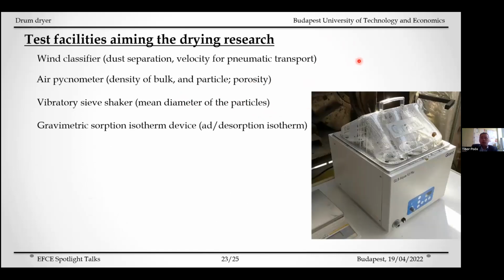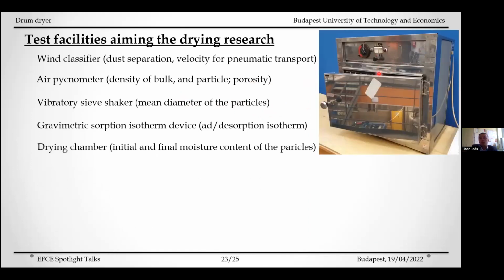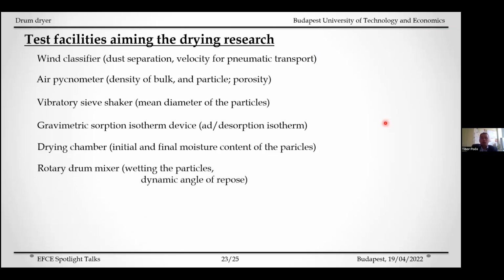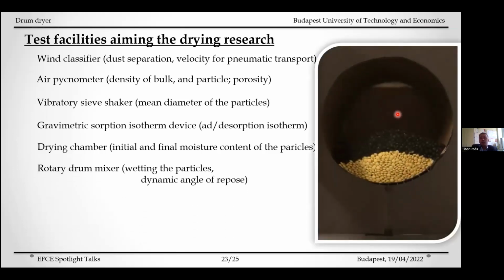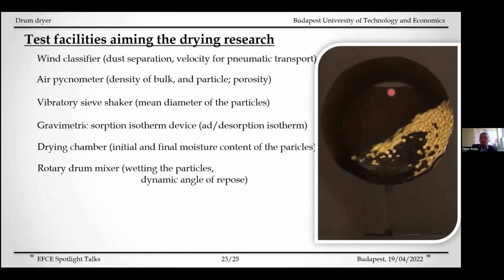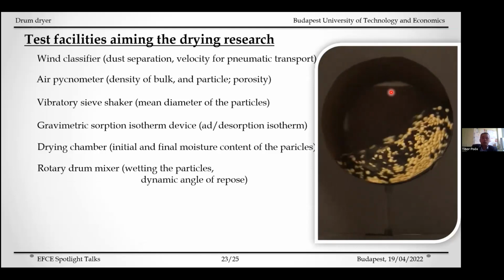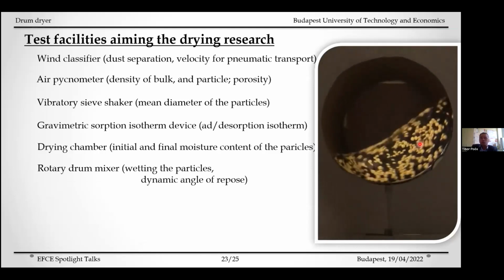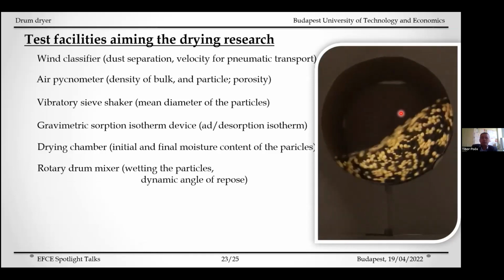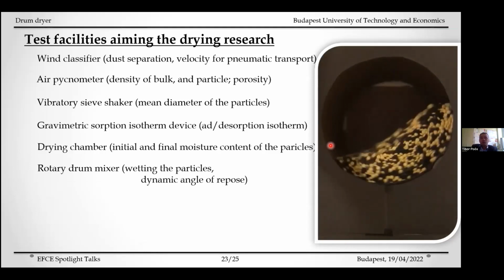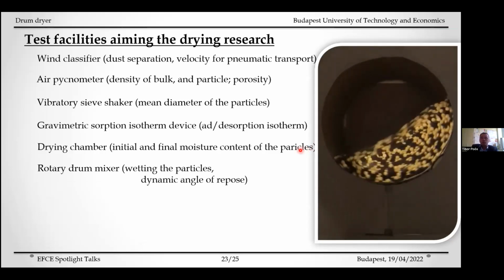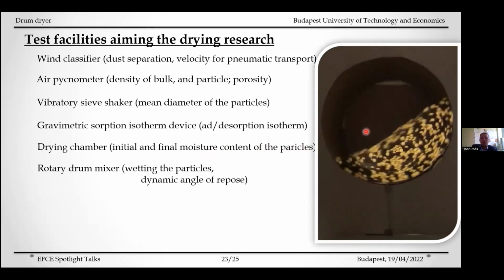An important drying parameter of the material is the desorption or adsorption isotherm, which can be determined with this gravimetric sorption isotherm device. This drying chamber has already been shown in the presentation. We use this to determine the moisture content of the particles. And in this video, you can see a rotary drum mixer used to wet the particles before the drying examination, but also we can use this machine to determine the dynamic angle of repose for DEM simulations. And we have already made examinations to determine the mixing index of the mixing process.